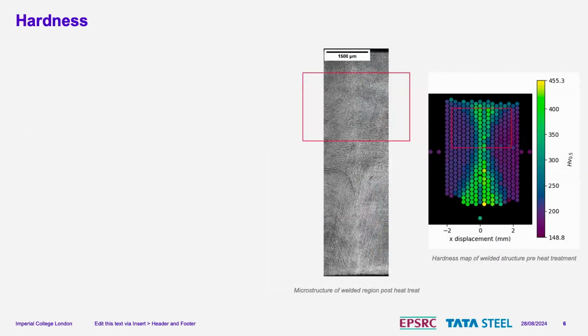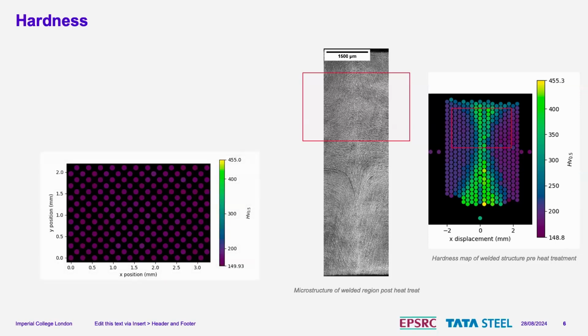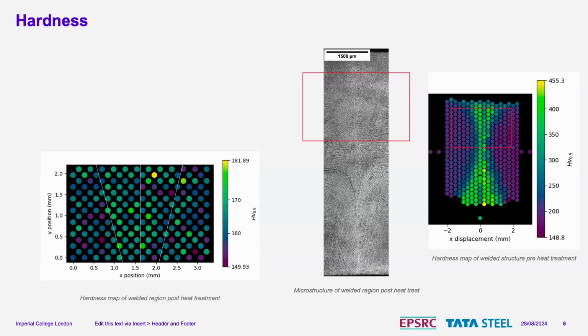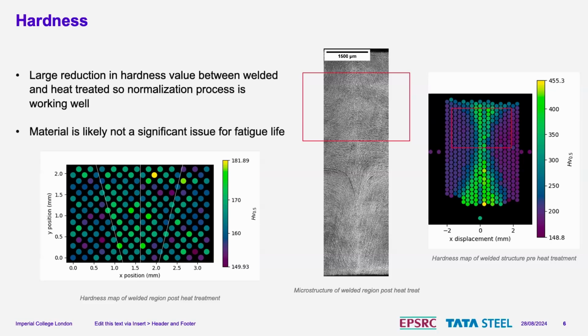So if we now take a smaller section of this, and I've just reproduced this one here. After it's normalized, I took another map, and this is my data. You can see we should have some weld lines, but we've got absolutely nothing. So if I just change the scale on this, you can see I've put in the weld there, and we've got a very, very slight variation, slightly harder in the weld region, but largely speaking, we have a fairly homogeneous material, and so the material itself is unlikely to cause any significant issues in fatigue.